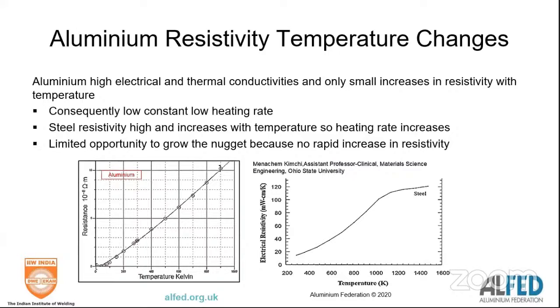The big problem that we have with heating aluminium is that the resistivity of steel significantly increases with its temperature. So the heating rate, amps squared times resistivity, of steel increases, but aluminium has only a small increase in resistivity. So you don't see the resistivity increase with aluminium that you see with steel. The heating effect is much lower when you're electrically heating aluminium. That means that you have problems growing the nugget.